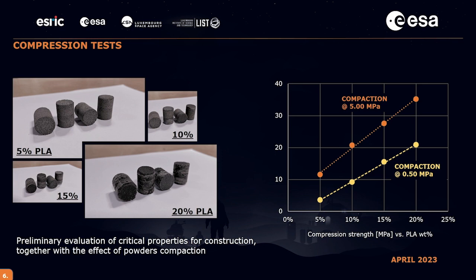It's in the range of 5 to 20%. And we also compare the effect of the compaction pressure we used. You see that the values of the compaction pressure are low. We are talking about 0.5 megapascal and 5 megapascal. And this is one of the most important things in this project. So it's really easy to compress those specimens with 5 megapascal.